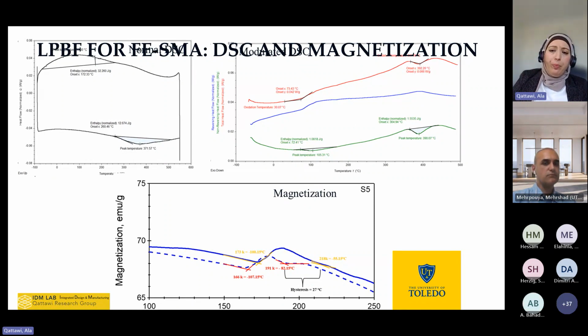And you can see that we get a good magnetization result for this alloy system specifically. It's not great, but it's an acceptable one compared to the traditionally manufactured one. And that gives us an idea of what's happening, why we're not actually achieving the same transformation temperature profile if we're using the same composition.